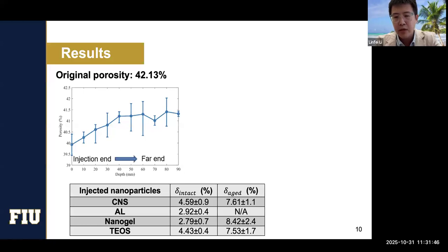Here we may need a little more information about the nanogel, because nanogel is a very unique material. When you add the basic cross-linker at the beginning, the nanogel is a nanoparticle, but over time this material is going to expand. Which means if you have an intact sample, once you inject the nanogel, it's going to expand and further damage your cement. It's kind of tricky. But for aged samples, since you already have large cracks, this kind of expansion actually helps to seal the cracks.